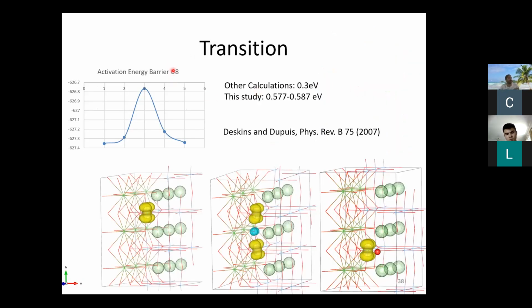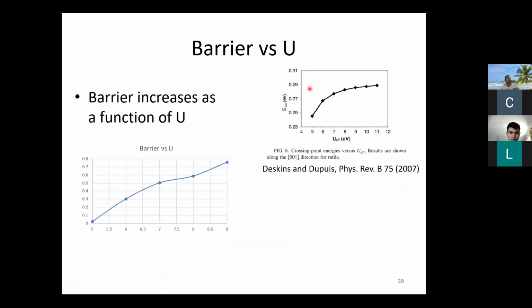From just using a standard value of U, we got barriers of almost about half an electron volt, which is somewhat comparable to some other calculations of titanium oxide systems, which were about a third of an electron volt. We varied the U value to see how the barrier would increase. In this case it increased almost linearly, whereas in other studies for titanium oxide, a similar system, it plateaued somewhere after 10. We didn't go far enough to see if we ended up plateauing.